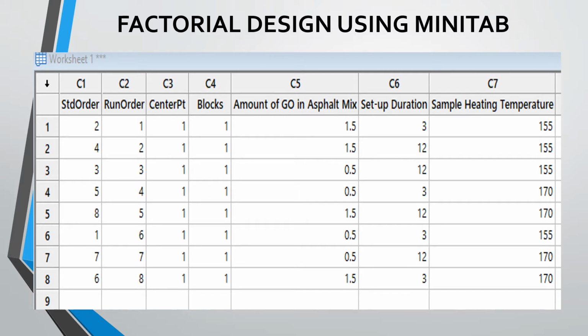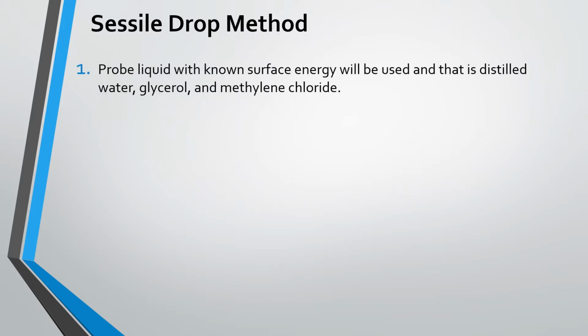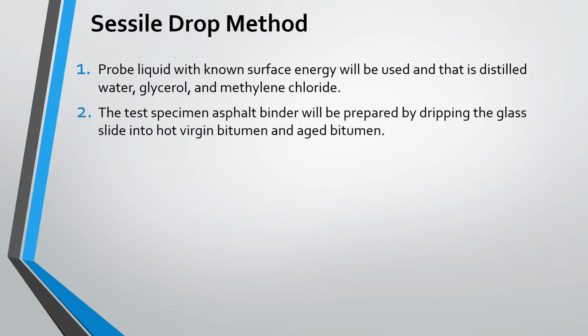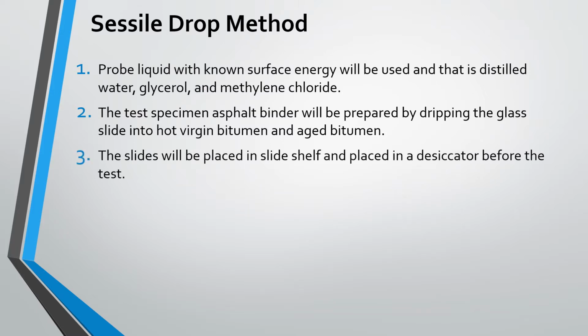In order to assess the surface energy of the GO-modified asphalt mix, the sessile drop method will be used. Probe liquids with known surface energy such as distilled water, glycerol, and methylene chloride will be utilized in the experiment. The test specimen, asphalt binder, will be prepared by dipping the glass slide into the hot virgin bitumen and aged bitumen. The slides will be placed in a slide shelf and placed in a desiccator before the test.